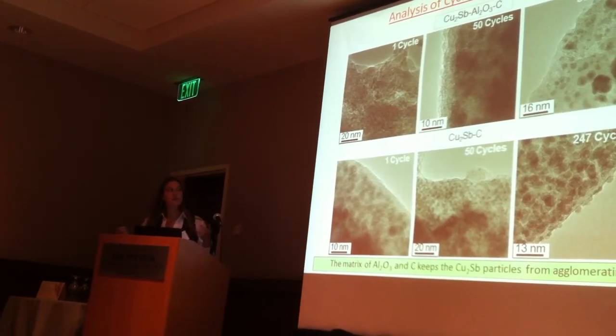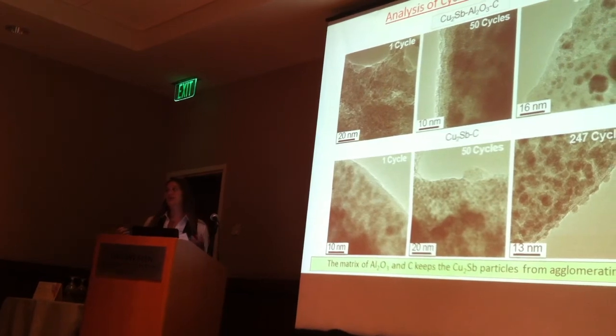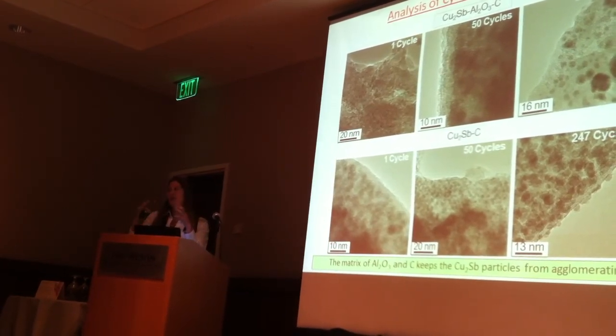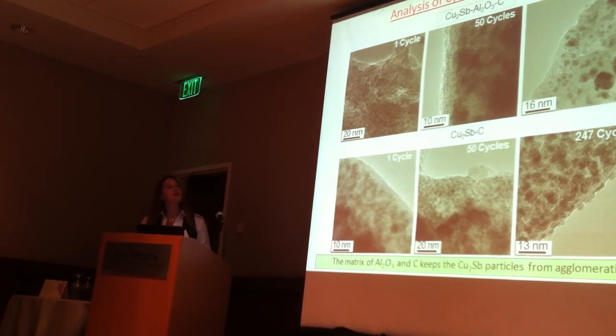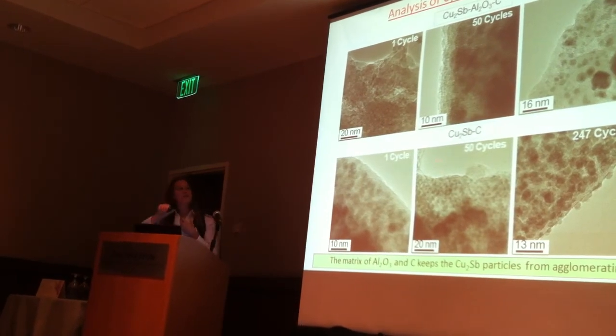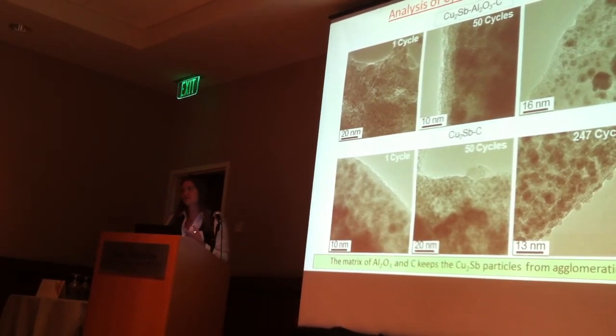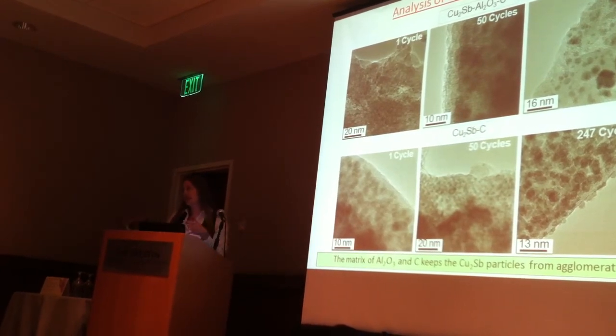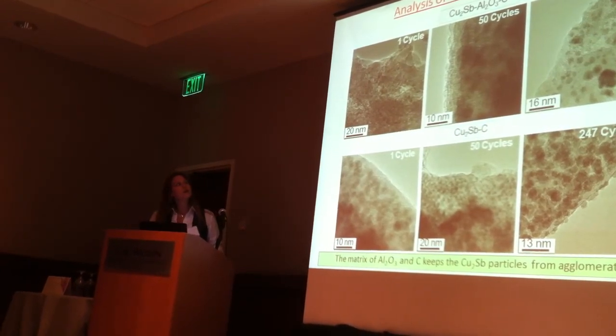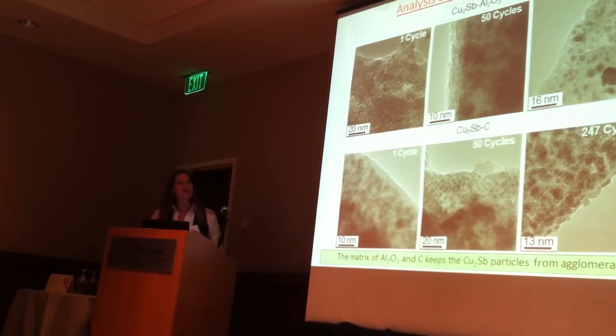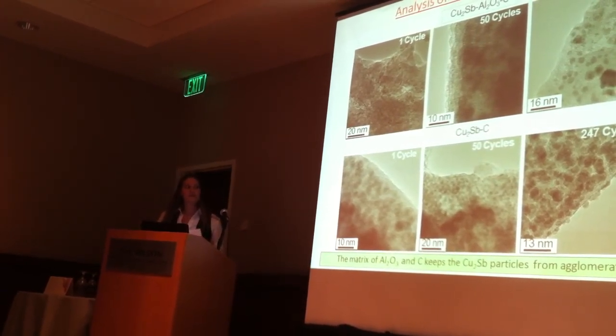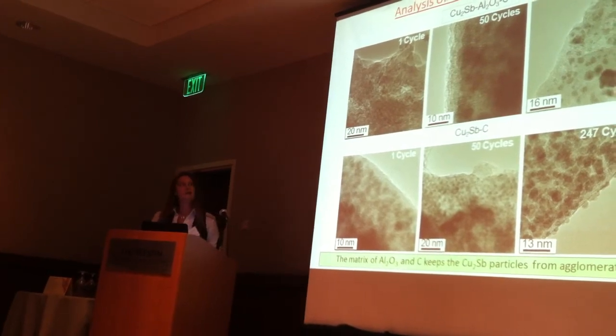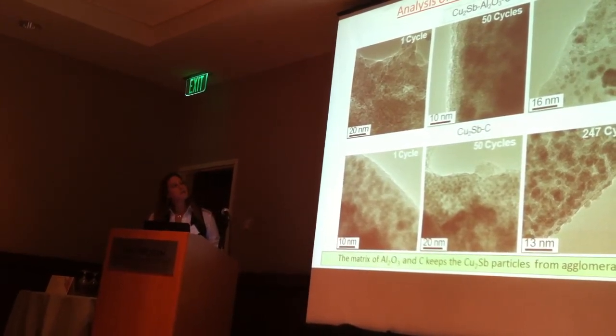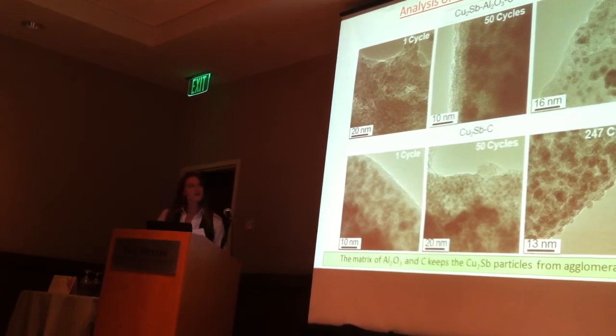And what's the most striking is they're separate from one another. They are in their own little zones, surrounded by this aluminum oxide and carbon. When you look down here, when you don't have aluminum oxide in your material, you see these particles are fused. They're stuck together, and this material, after 247 cycles, is not offering any capacity. It has catastrophically failed at that point. So, aluminum oxide is solving the problem of this agglomeration that ruins these battery materials, which is pretty exciting.